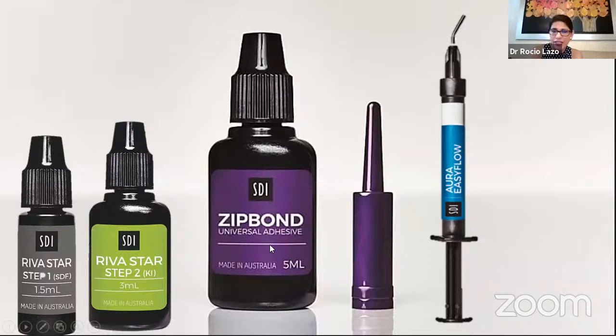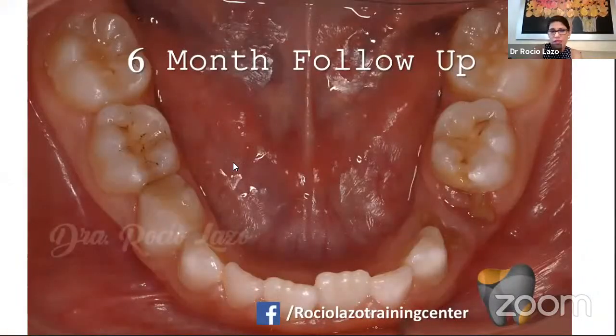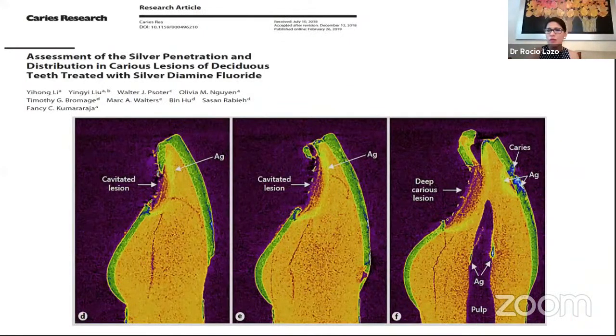With this universal adhesive I don't need to use the orthophosphoric acid. So I apply the universal adhesive, photopolymerization, and then the flow resin. So this is another SMART technique. The SMART technique is not only with glass ionomers. I repeat, you can do it with resin. Okay, so the problem is not the color. The problem is not whether you are doing non-restorative or restorative with the SDF. The problem is the penetration, that it is a high penetration.